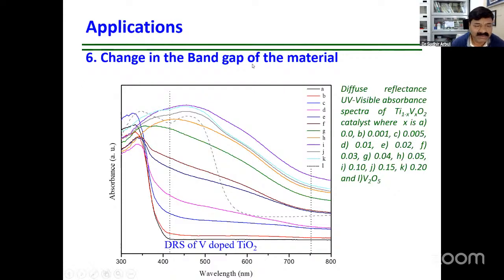See here what we did: we used UV-visible spectroscopy to observe the change in the band gap of materials. Here we doped vanadium in the TiO2 lattice. The black one is the UV-visible spectrum of our TiO2. The dotted line is the spectrum of vanadium pentoxide, V2O5. See the difference. As you increase the vanadium doping in the TiO2 lattice from 0.001 to 20 mole percent, see how nicely the visible spectrum sits. It can cover the whole solar spectrum for photovoltaic applications. So using UV-visible spectroscopy, we can check the absorption profile of our material and get an idea of its band gap.